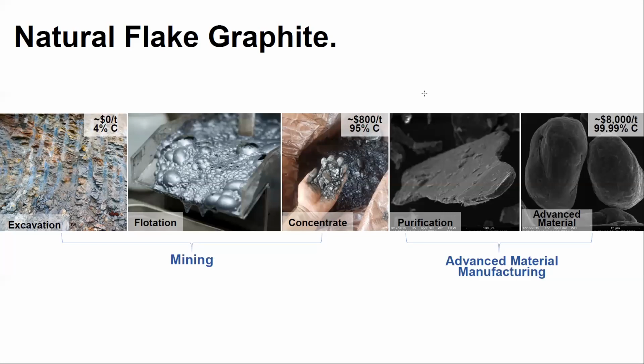So we would take that run-of-mine graphite concentrate and now upgrade it by purification. This is typically done using hydrofluoric acid or heat treatment. And then the purified graphite gets micronized, it gets sized, shaped, and gets a specialty coating to make it ready for the anode of a lithium-ion battery. And there's an order of magnitude difference in the selling price by upgrading this material from a concentrate to a specialty material.